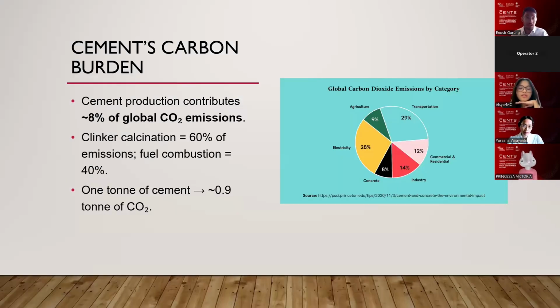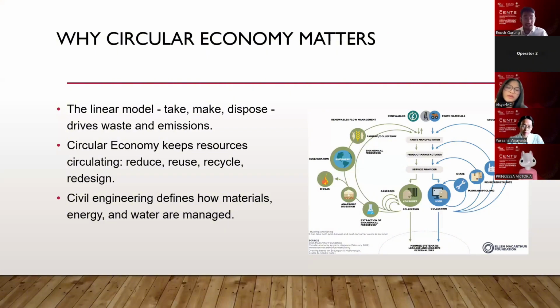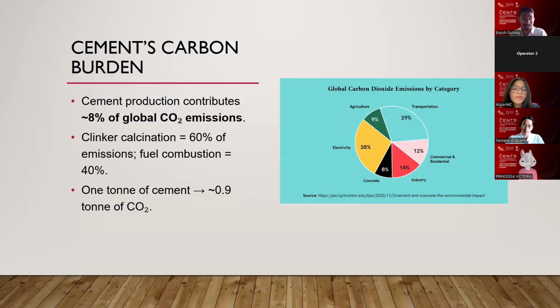Now, the cement carbon burden. Cement produces 8% of global CO2 emissions. Can you go to the next slide, please? One ton of cement produces around 0.9 ton of carbon dioxide. One fact is that Indonesia reduced its cement CO2 intensity from 725 to 614 kg of CO2 per ton from 2010 to 2020. This lowered the emission per ton, but the total national emission rose because production increased. Next slide, please.